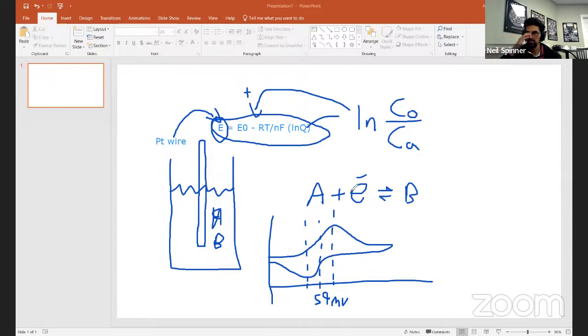And to address a little bit more what this difference means, because you can actually get a difference that's different depending on the kinetics of your experiment, right? If you're oxidizing something, you may see in another voltammogram that the two waves are a lot farther apart. That has to do with the kinetics of the electron transfer. It means it's a whole lot easier to go one way. That's like the alpha of your system. It's a whole lot easier to go from A to B than it is from B to A. It's a slower process. So the distance between your anodic and cathodic waves has to do with kinetics.